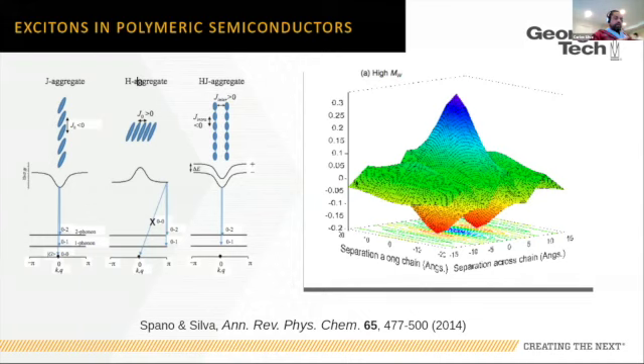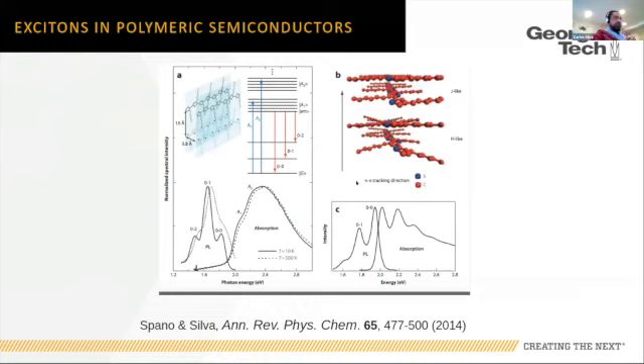Now, this is all that I'm going to say about aggregates and polymers, other than they are hybrid HJ aggregates. And because of the hybrid nature, we can turn an H aggregate into a J aggregate. Here's P3HT, and we can do this with the same material, the same batch. P3HT is predominantly an H aggregate when we cast it just from solution.